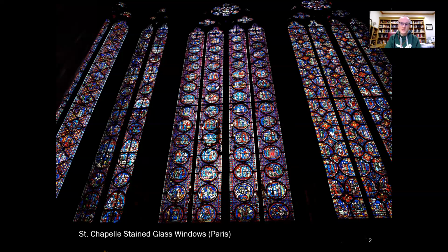Now, the reason I bring it up for this lecture is that if you look really closely at any of the individual pieces of stained glass in these windows, you might notice that some of the glass panes are a little bit thicker at the bottom than they are at the top. And this observation has led many people to believe that the glass is flowing over time. If they assume that the thickness was uniform when the glass was first installed, then over time, the assumption is that the glass is very slowly flowing, gradually becoming thinner at the top and thicker at the bottom.